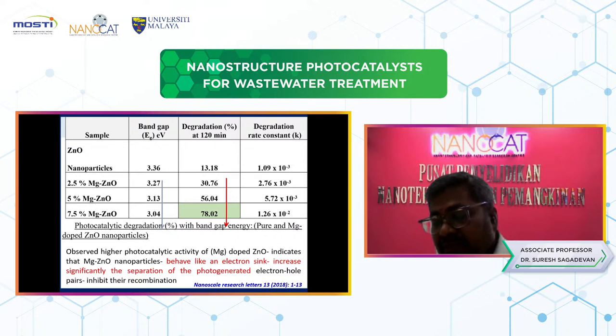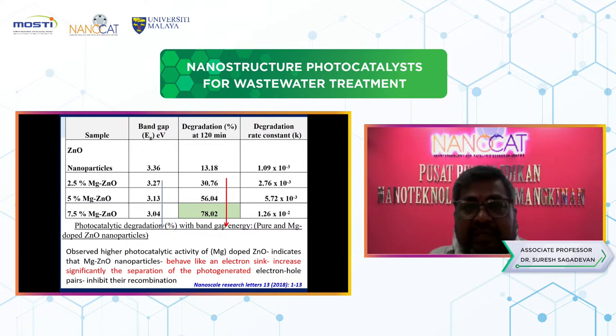Therefore, it is observed that 7.5% Mg-doped zinc oxide has shown a maximum degradation of 78% compared with the other doping concentrations. It is also noted that at the higher doping concentration of 10% in zinc oxide, the photocatalytic activity is reduced, because of the physical defects as well as the increase in the oxidation states of cations, so that decreases the degradation. So this material is also very potential for degradation as well as wastewater treatment application.